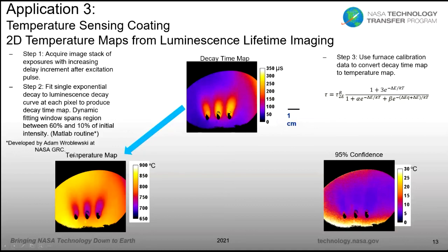They're interested in the temperatures, so we have to convert each decay time in our map to a temperature. That's where we go back to this relationship between tau, the decay time, and capital T, the temperature, where fitting the furnace calibrations gives us all the other coefficients. Using that, we can convert our decay time to temperature. So now we have the useful temperatures. You can see the uncooled regions are at about 900 degrees C, and cooled regions are 100 degrees C or so cooler.